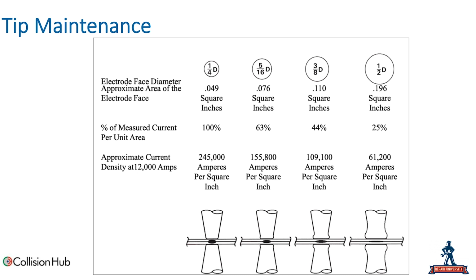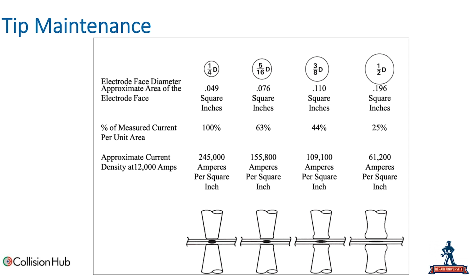Now, as that begins to mushroom, we start getting to 5/16 of an inch, 3/8 of an inch, 1/2 inch, which we probably would never get to with a collision repair spot welder, hopefully. Anyways, you can see that the amperage density goes down dramatically. As that amperage density goes down, more amperage is required to make the same quality of weld. So if you have that mushroomed head on it and we're not increasing the amperage, we're going to have a weaker weld. There's just absolutely no way around that.